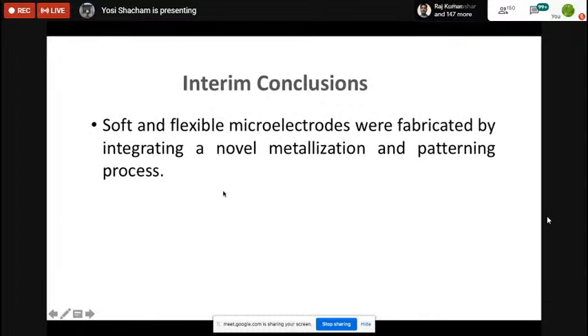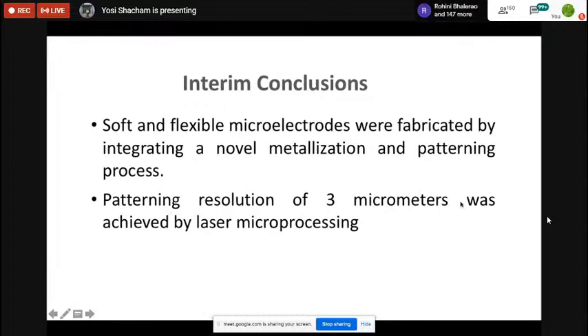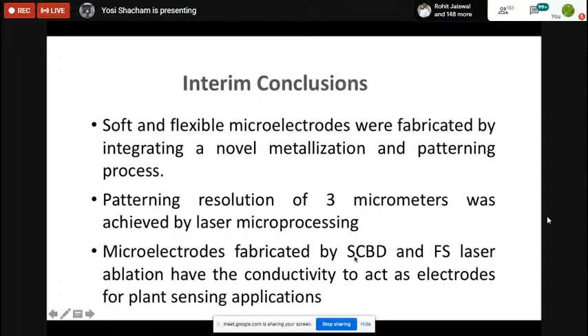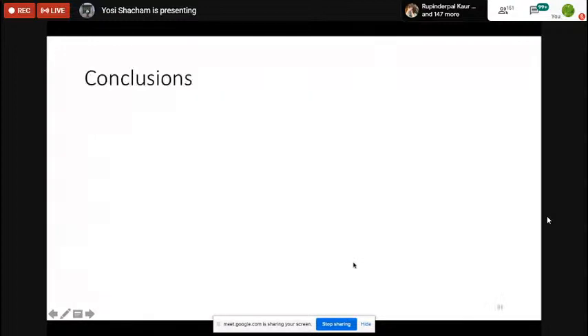So to summarize this talk, and I promised Ragini that it will be between an hour to hour 15, so we are close to the end of this talk today. The interim conclusion about what we do is that soft and flexible microelectrodes were fabricated by integrating a novel metallization and patterning process. We can go down to 3 microns by laser microprocessing. The microelectrodes fabricated by the supersonic cluster beam deposition and femtosecond laser have the conductivity to act as electrodes. We use it for plant sensing, but Professor Milani is using it for electrodes for the brain and electrodes for the skin. And there are a lot of applications for this technology now being investigated.